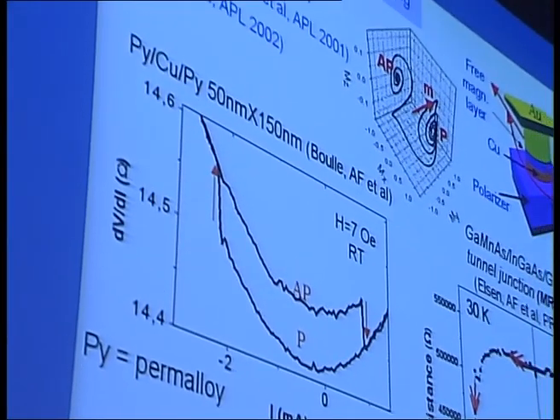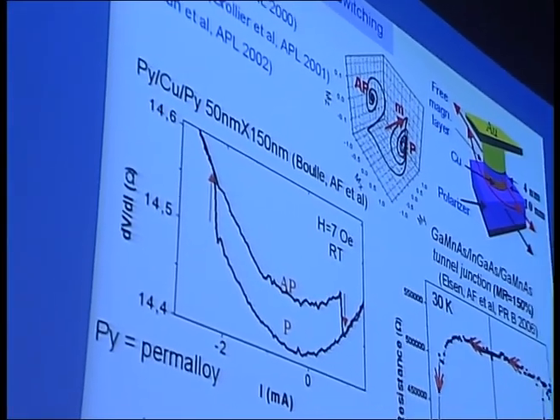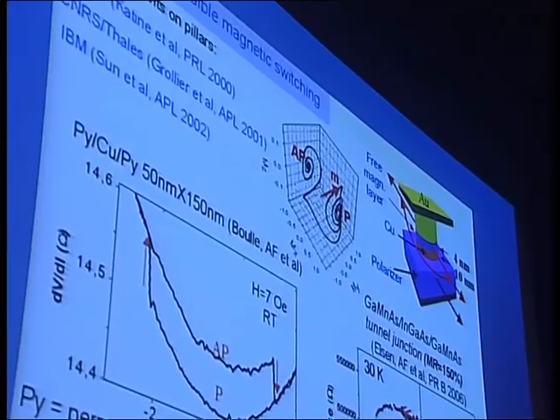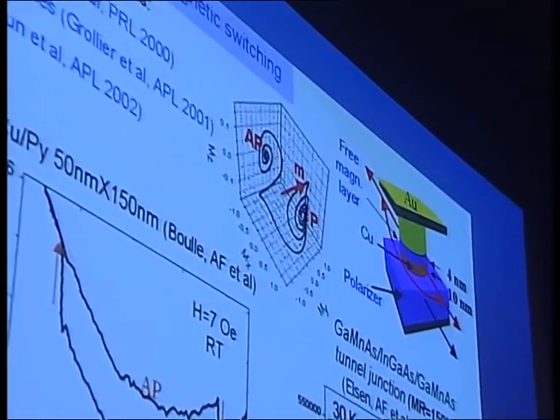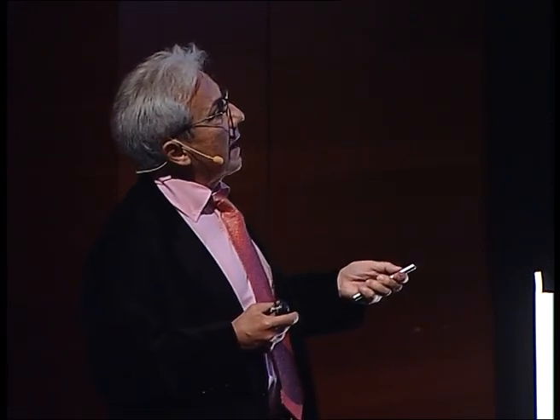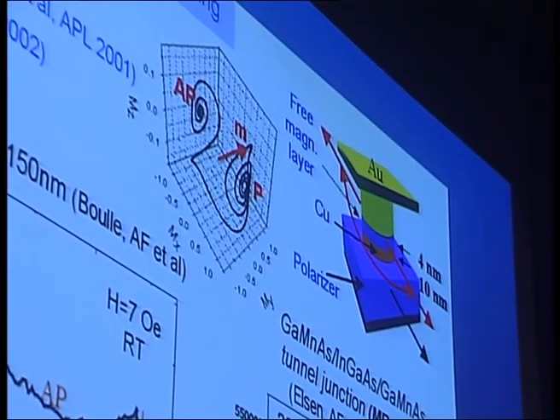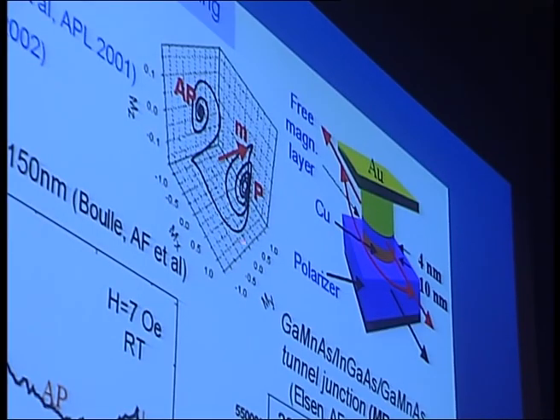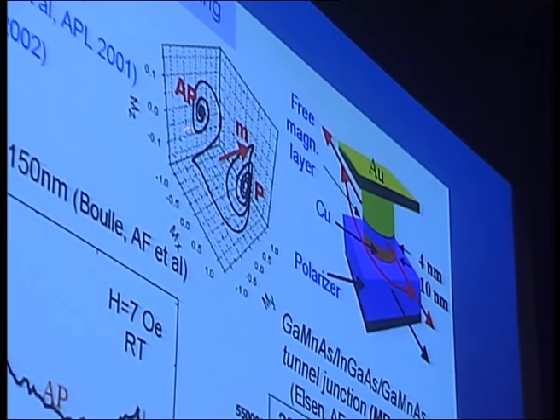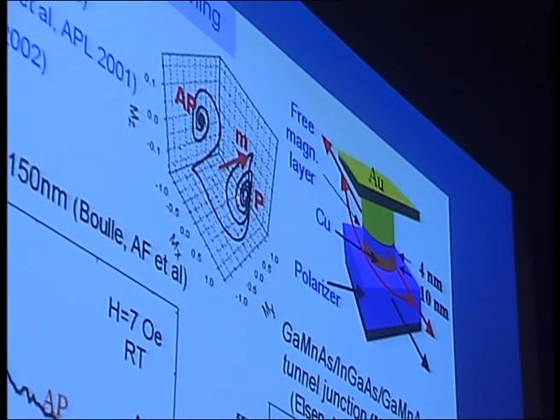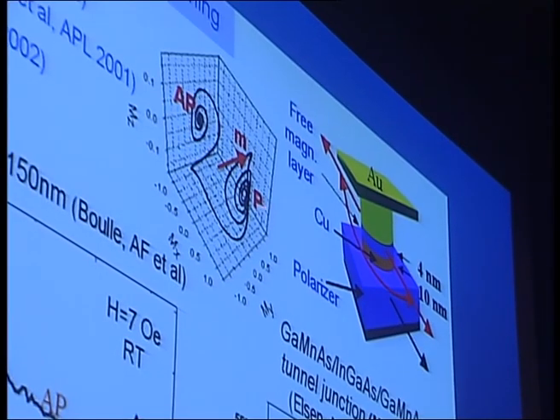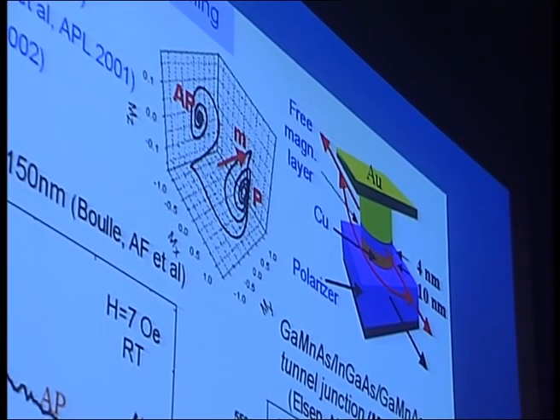The switching trajectory is not as simple as you can see on this figure. In fact, the spin transfer torque is equivalent to a negative friction, so it can progressively enhance a small fluctuation of the magnetization to finally switch the magnetization to the other side. And the reversal of the magnetization is detected by the GMR effect, by looking at the increase of the resistivity between parallel and anti-parallel.